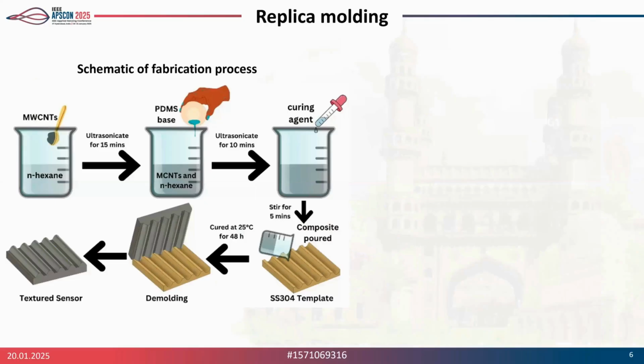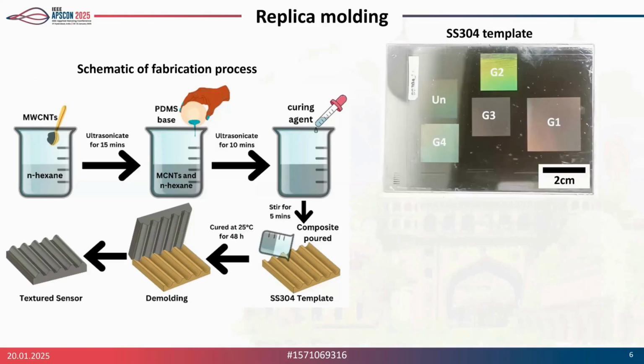So we use a very simple methodology known as replica molding, wherein we made a PDMS and carbon nanotube composite and poured it on a stainless steel template, which was a laser textured microgroove. Then we cured it for 48 hours at room temperature, and after that we demolded it.